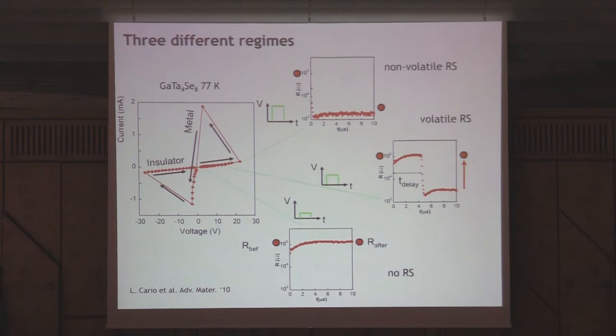It's qualitatively different. Okay, so we go back to this GTS, this beautiful Mott system, and the early investigations of the group in Nantes show that there is non-volatile resistive change. You see you have a system which is in a high resistive state. This is current, this is voltage, and then by a strong voltage, you can switch it to a more conductive branch, so you have this new IV, but this can be undone and go back to this thing, so you have the non-volatility that I mentioned before.